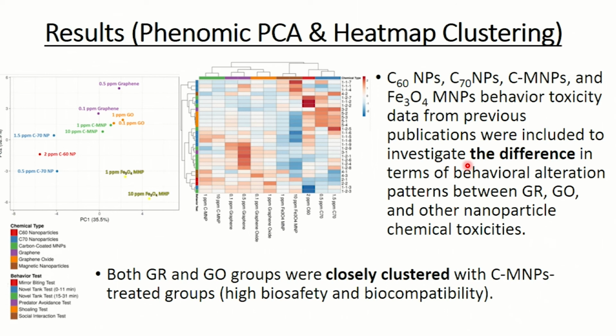Based on the phenomic results, we found that both graphene and graphene oxide groups were closely clustered with carbon-coated magnetic nanoparticles treated groups. After further inspection, we found that even though slight alterations in zebrafish behavior were still detected, surface modifications in magnetic nanoparticles improve their biosafety and biocompatibility. This grouping is possible since graphene and graphene oxide treatment did not trigger significant alterations in zebrafish behavior in the current study, which is somewhat similar to carbon-coated magnetic nanoparticle results.